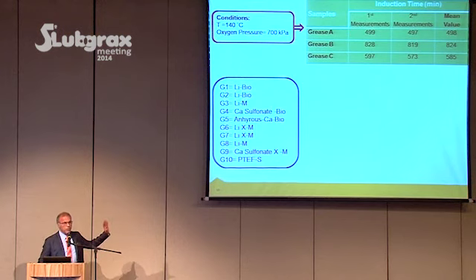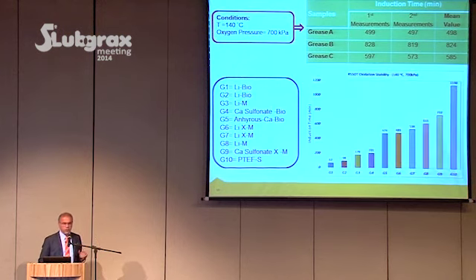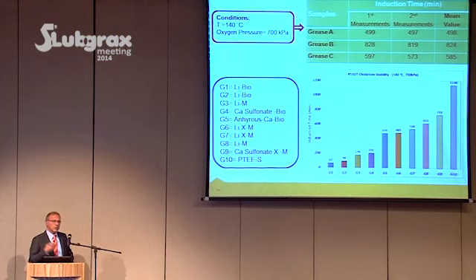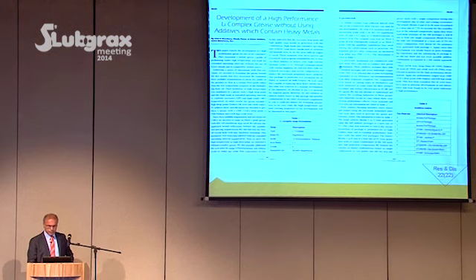On the left side, you have those references from the previous slides, and here is the chart. As you can see, these are fully formulated. In fact, if we compare group 2 with naphthenic oil, the only product which can beat this is PTFE plus synthetic oil. All others are below this. And this is not something which we have done; we just sent it to that laboratory and they performed it for us. This, plus the standard oxidation test with 2 psi, emphasizes the great oxidation stability which we got in this combination.